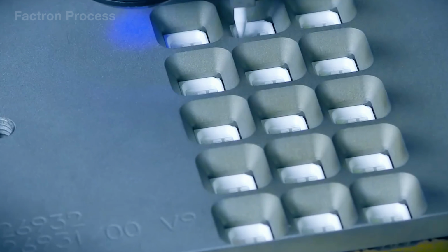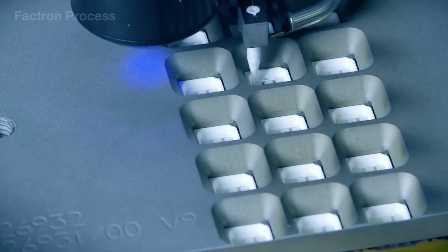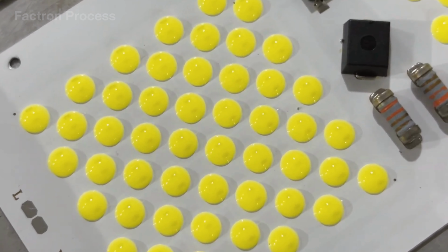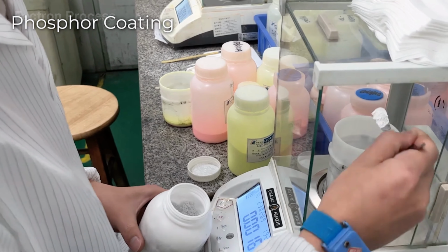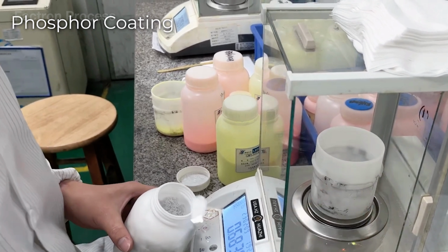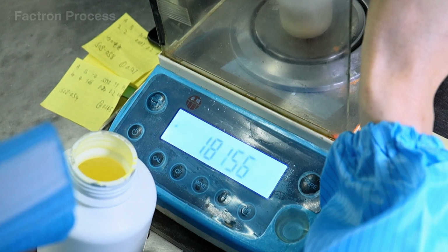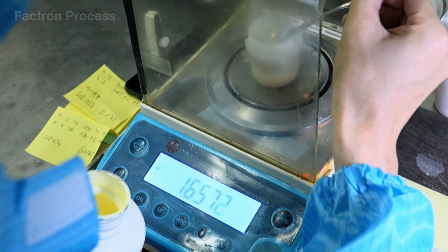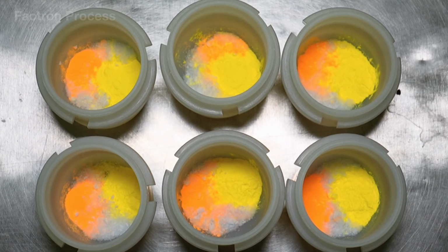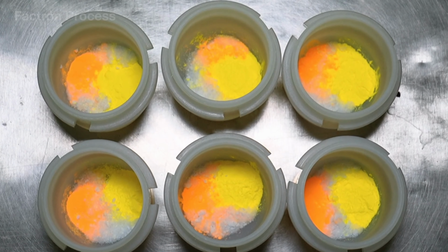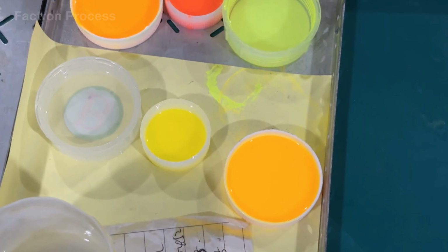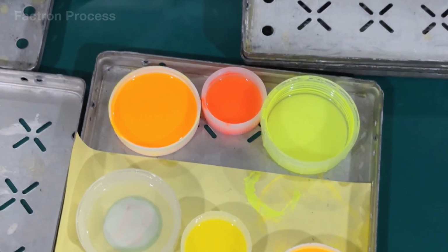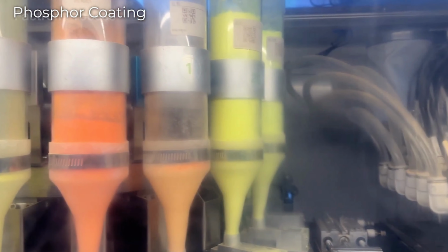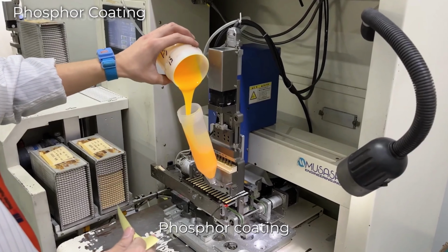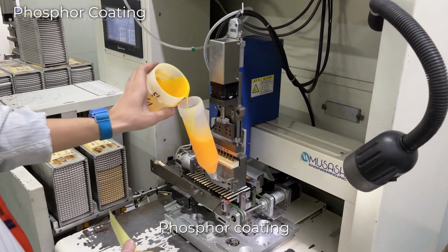After the gold wire bonding and initial inspection are complete, the LED trays are transferred to the phosphor coating area, the stage that determines the product's final light color. Here, phosphor powder is weighed using equipment with a precision of up to 0.0001 gram. Depending on the required color temperature, engineers blend several types of phosphor in carefully calculated proportions, then place the mixture inside a high-speed mixer to disperse it evenly throughout an epoxy solution.